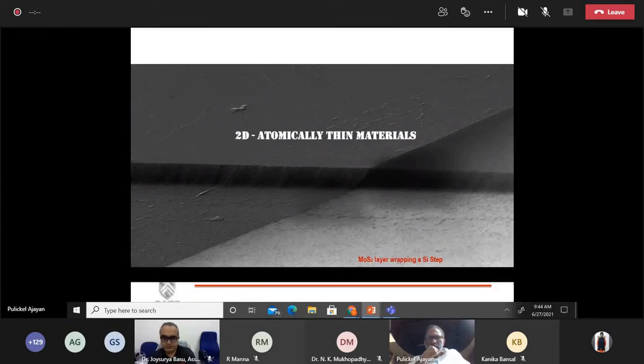Well, in the last part of my talk, let me come to these 2D atomically thin materials, which I have mentioned a few times. But our focus in recent years has been trying to understand how these structures can be, again, manipulated. So this is an image showing an MoS2 molybdenum disulfide layer sitting on a silicon step. And what you can see is the essence of what 2D materials might look like, especially when you're starting to think about making devices and so on. So you can see all these small defects that appear, like blisters or wrinkles, and those are unavoidable, really. And that's essentially the nature of this kind of system.